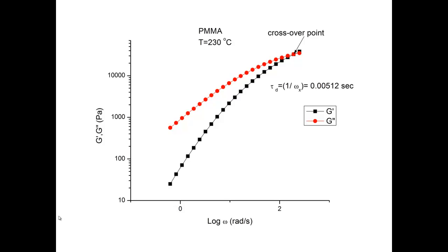So here we see this for polymethyl methacrylate at 230 degrees C. So again, it's 125 degrees above Tg. The reptation time is indeed very small. It is 5 milliseconds, 5.12 milliseconds.